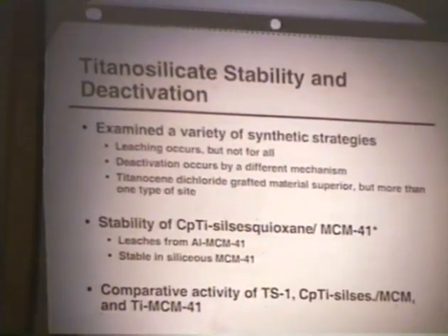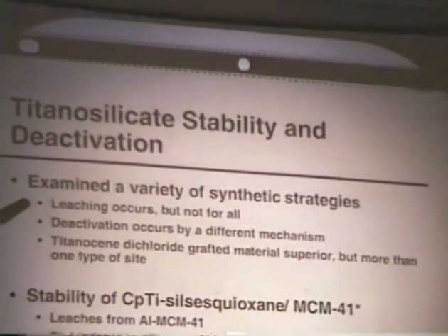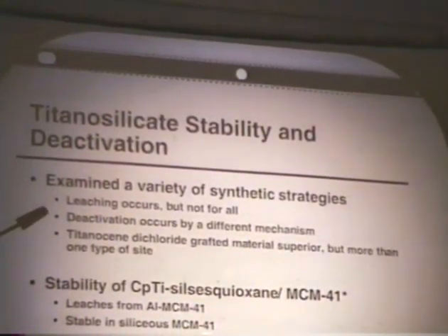I'm going to skip right to the punchline here because I think it helps as we go through this to understand what I'm trying to say. First, I'm going to tell you that leaching occurs in these materials depending on how they're made, but not for all of these materials. In other words, synthesis is important in determining if they'll lose titanium or not. But it turns out that the loss of titanium really isn't important. These things deactivate by a different pathway that does not have anything at all to do with the leaching.